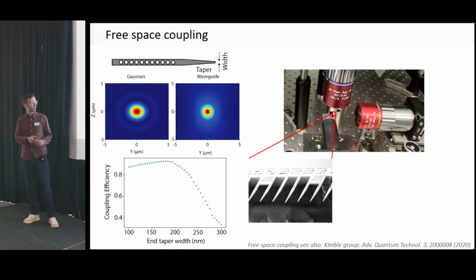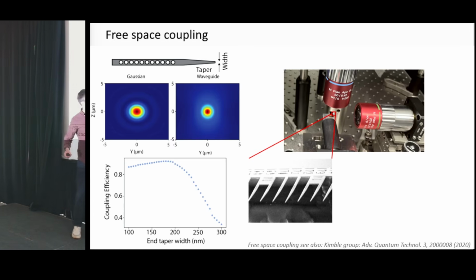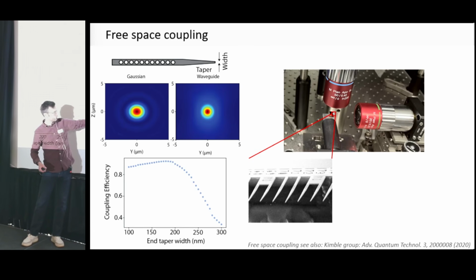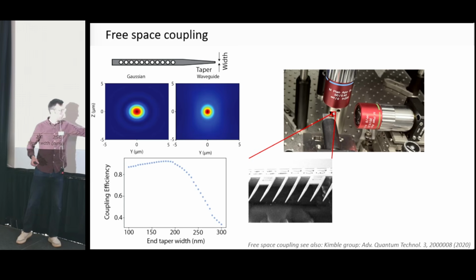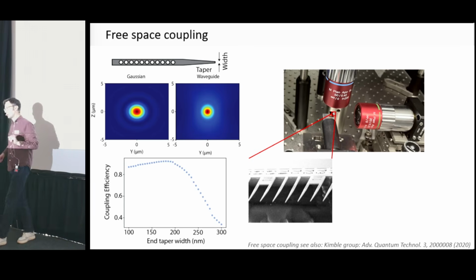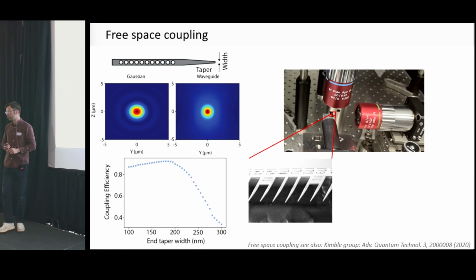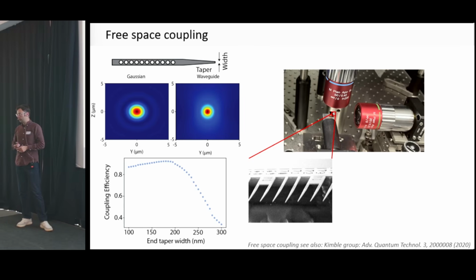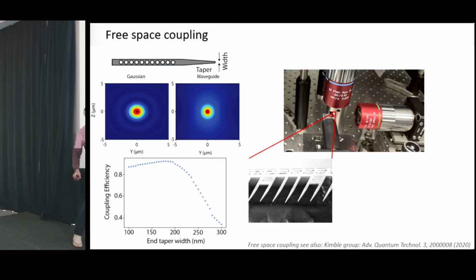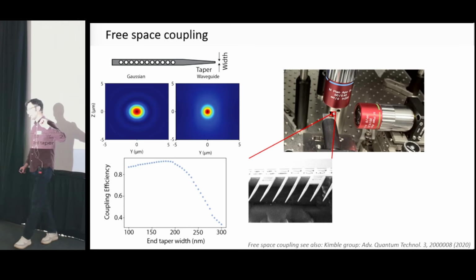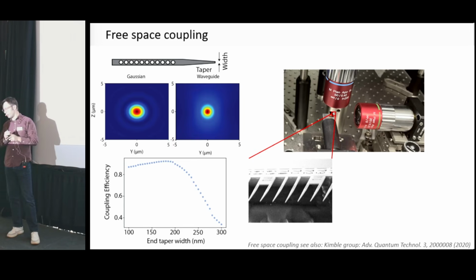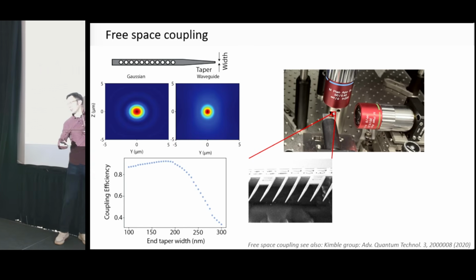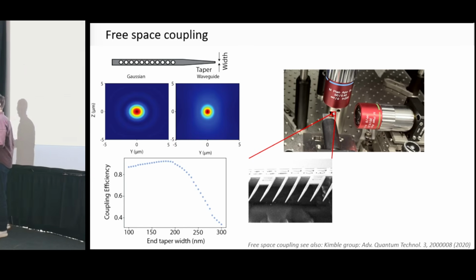So this is silicon nitride. With KOH and the selectivity, you can take this away, and it's about 300 micrometers thick. So it actually works quite nicely. All right, thanks. But you don't see any bending of your freestanding structures? No, we don't see any. Maybe there's a tiny bend, but this works well. The only thing that's a little bit tricky is that you have to check in real time, because if you etch too far, then they collapse and fall down. All right. Thanks.